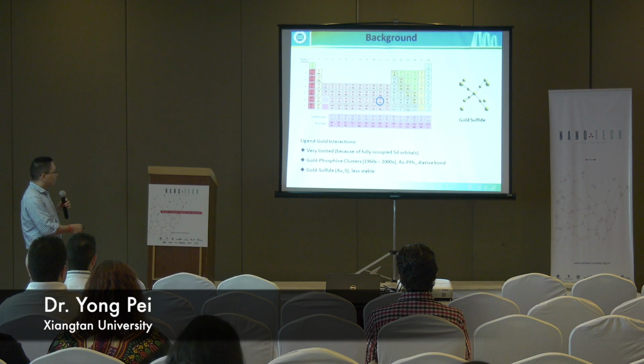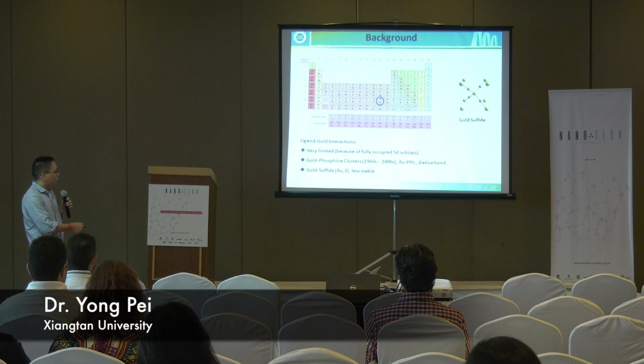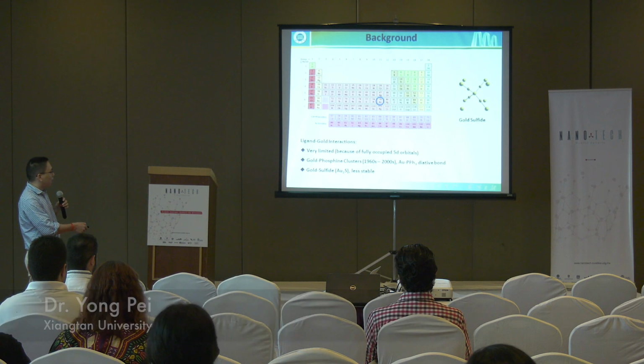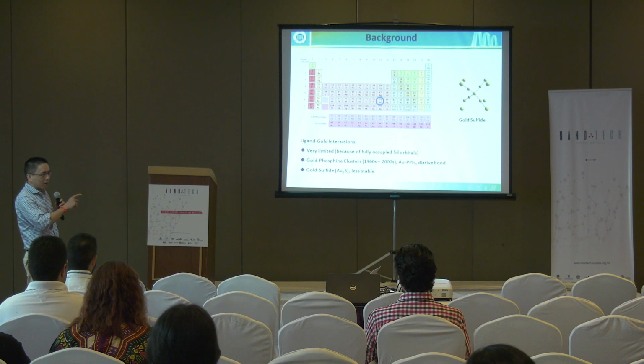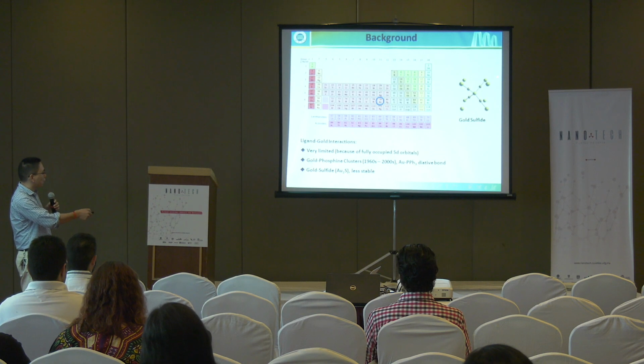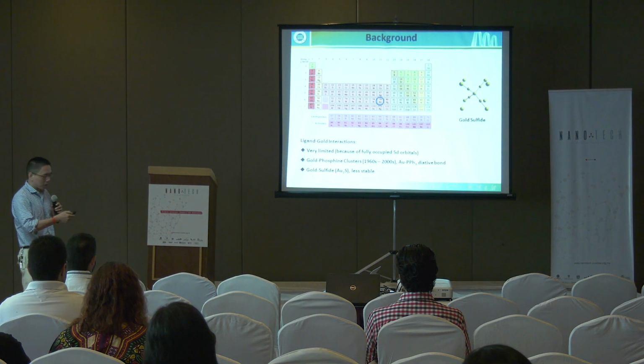The well-known gold ligand compound was the gold phosphine clusters. This was first reported in the 1960s, and has seen 40 years of study. In this cluster, gold and phosphine form a direct bond. This is top-site adsorption. Another well-known compound is the gold sulfide, but this is less stable. The crystal structure of gold sulfide is here. Each gold is coordinated with four sulfur atoms in the lattice.